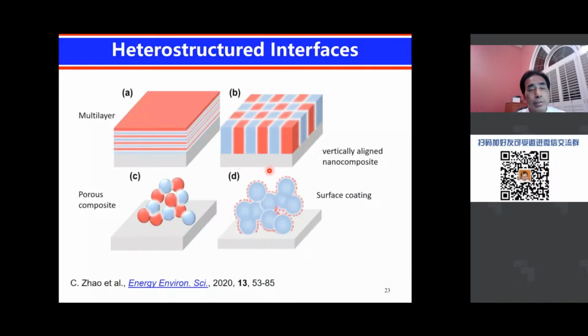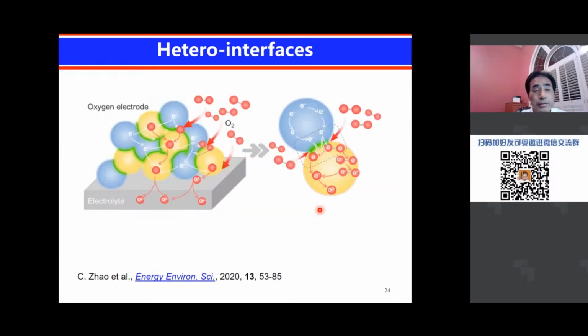Now, for fundamental study, typically we can use different ways to create a structure. For instance, by creating a multilayer, you can use PLD, ALD, with atomic precision to put down different layers of atoms and create a multilayer and create hetero-interfaces. Or you can have vertically aligned nanocomposites. Those architectures or configurations give us the ability to create hetero-interfaces, and by carefully controlling the chemistry and the structure, you can get the hetero-interface.